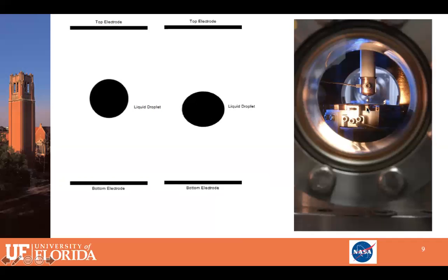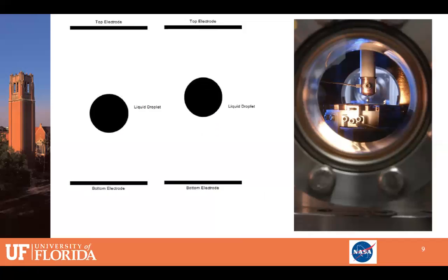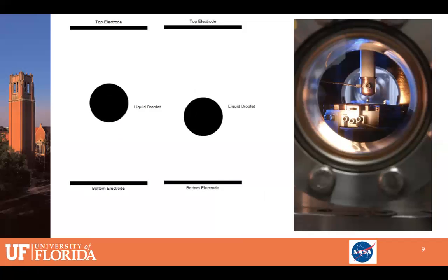If the frequency is large enough, this sphere of liquid will then ultimately undulate as seen in the movie and in the depiction on the left. The frequency at which it begins to undulate is called the resonant frequency. This means that the frequency of the imposed alternating field is commensurate with the natural frequency of the sphere. This resonant frequency, when matched with the natural frequency, causes this sphere to go into all manners of modes, the lowest mode being shown here.